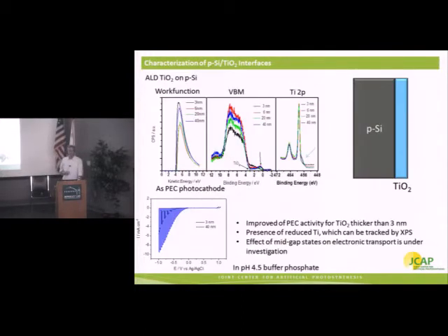So that led us to another line of interface engineering. And in this case, what we want to do is introduce a thin interfacial layer which can transport charge, but which also passivates surface states on the semiconductor. And one system that's quite promising is TiO2. And in particular, some of the recent advances in atomic layer deposition allow for atomic control at very, very thin layers that are completely conformal. And that's what we need if we want to also introduce stability into these systems.